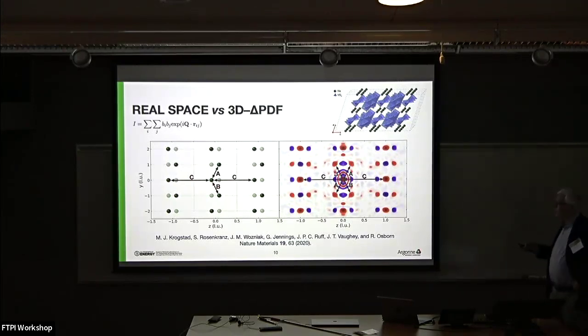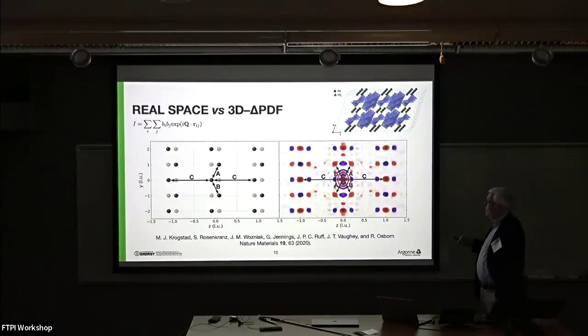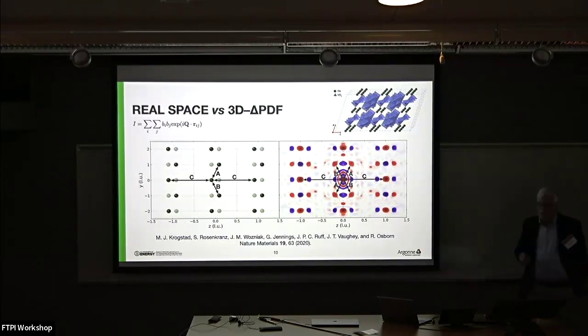But what this means is you can actually read off the correlations without doing any modeling. You literally see that there are these zigzag correlations along the ladders, and you can tell, for instance, that the neighboring ladders are in phase. And indeed, you can determine correlation lengths for those precisely without actually having done any modeling at all.